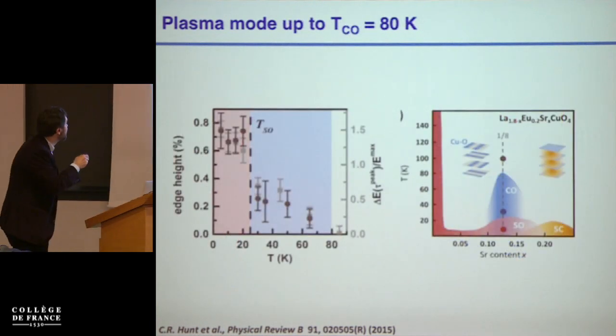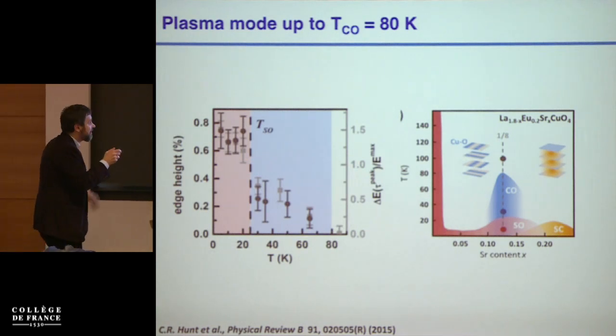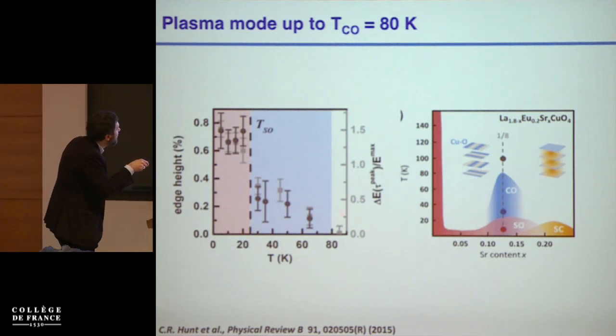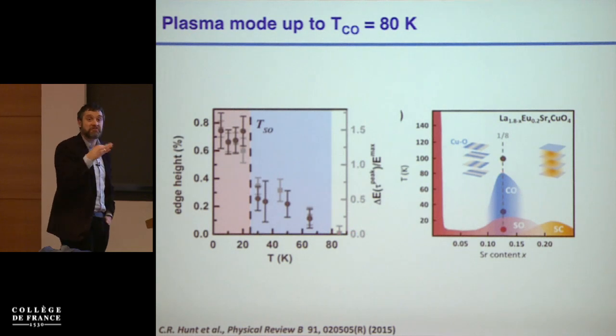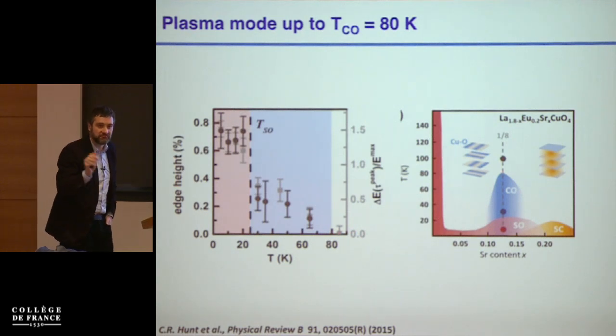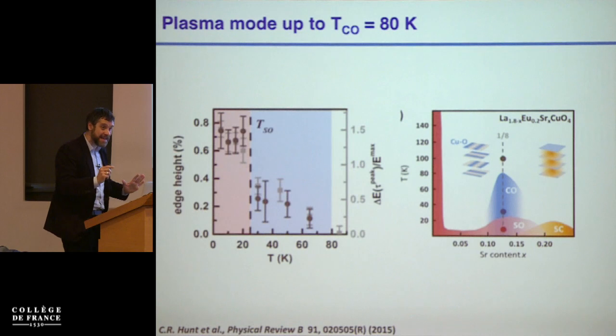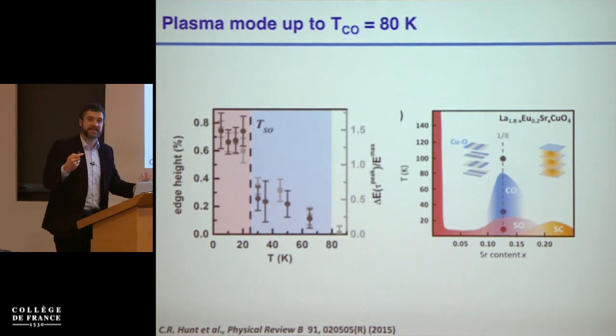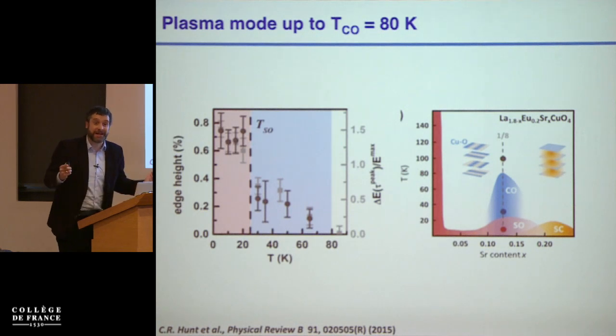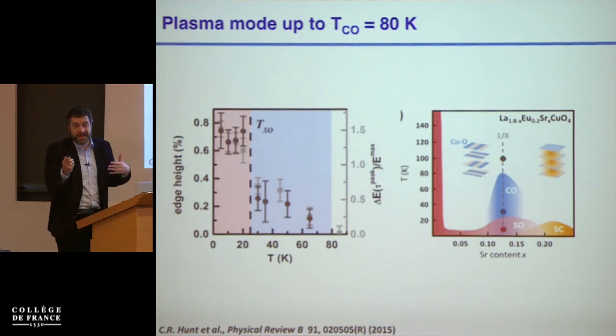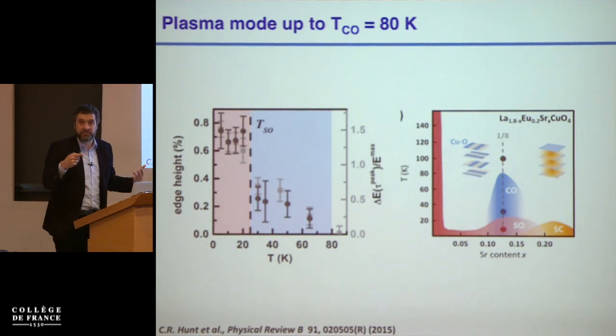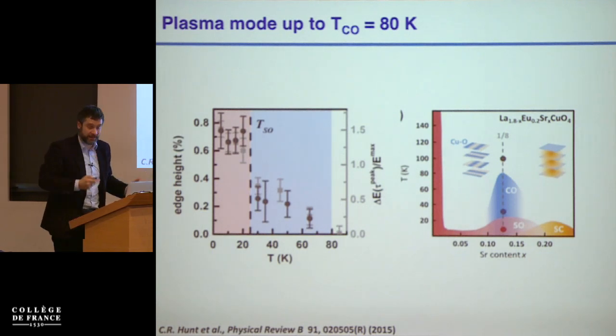And in fact, details aside, I can observe a finite edge all the way to exactly the charge order temperature at this 1/8 doping. So this is again something that is satisfying in the sense that nobody's really too surprised by this. I have stripes. There's nothing that tells me that if I melt those stripes, I should not have an 80 Kelvin superconductor starting from a 1 Kelvin superconductor.